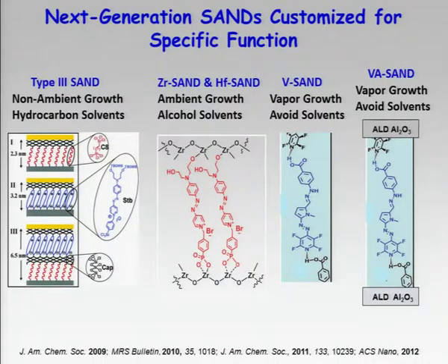So now we have new generations of sands, and I'll tell you a little bit about them, that you can process under air, and they're multi-layer structures with zirconium or hafnium layers, and the same kind of pi organic sandwiched in between. The pi organic gives you the large K. The saturated organic parts, as I show you here, and the hafnium dioxide give you the insulating characteristics.